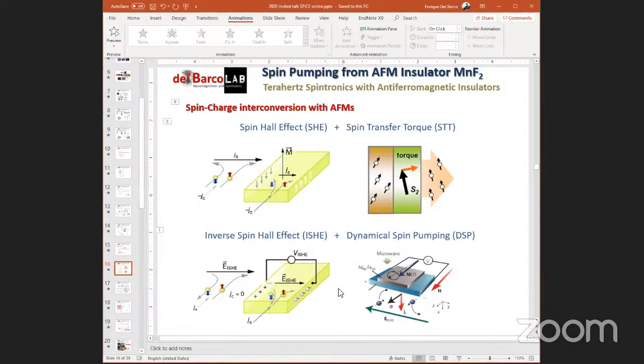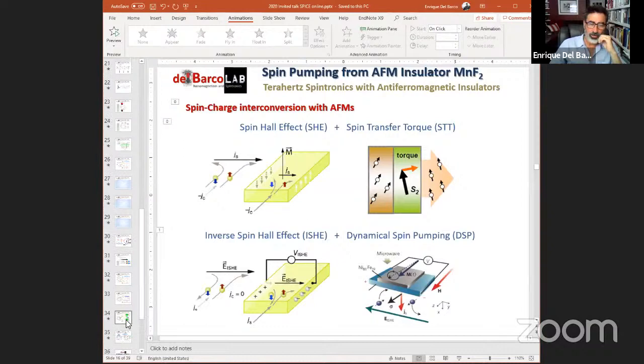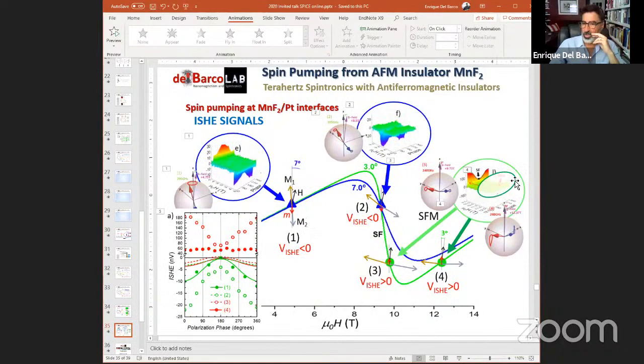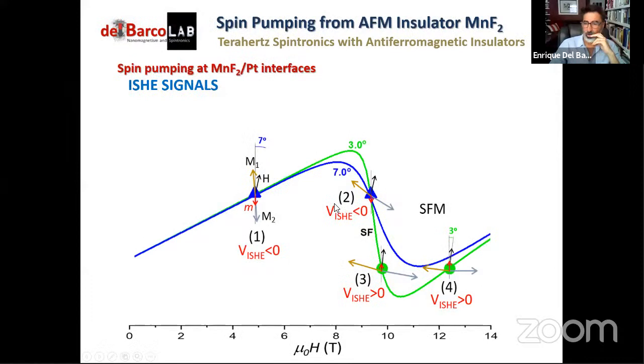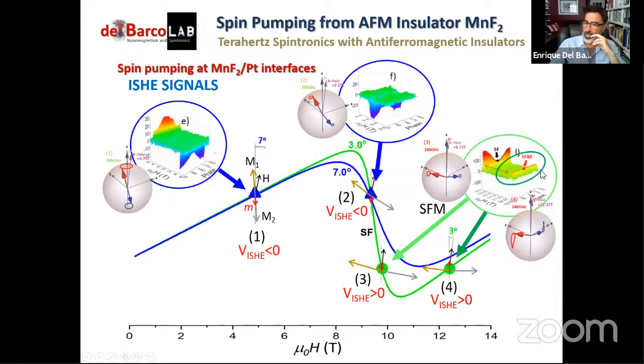Well, we believe that it is most likely coming only from the Seebeck effect. The reason we believe this to be the case is because we don't see any modulation, as we had seen at lower magnetic fields, right? There is no modulation, and also the signal is positive and opposite to the one that we would expect from coherent spin pumping. And indeed, if you connect this that I'm pointing here, I don't know if you see my cursor, but let me just use the pointer. So if this line, you can actually make a connection to the spin flop transition.